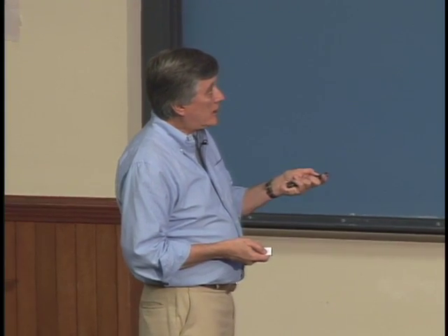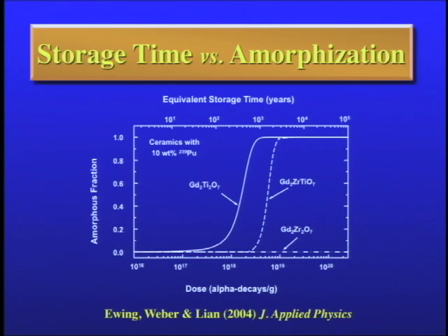For the gadolinium titanate, halfway in between zirconium and titanium and the gadolinium zirconate, we can estimate very accurately the amorphous fraction, how much of this material was converted to this amorphous state as a function of dose. What you see is the gadolinium zirconate just becomes crystalline defect fluoride, but never becomes amorphous. The gadolinium titanate would be fully amorphous in 1,000 years, and the gadolinium zirconium titanate would be somewhere in between.